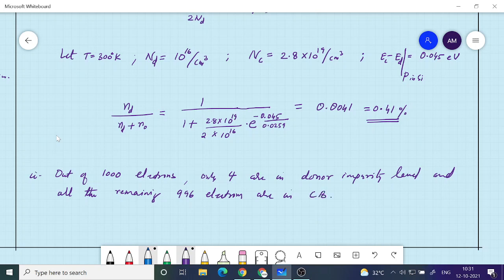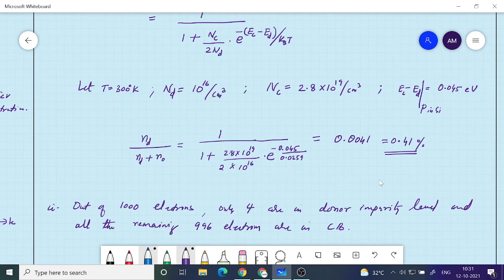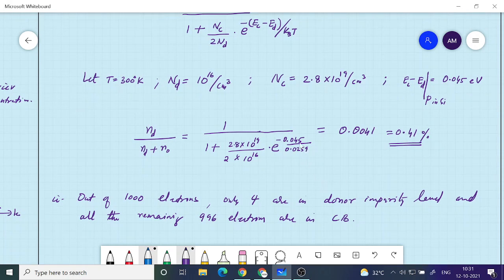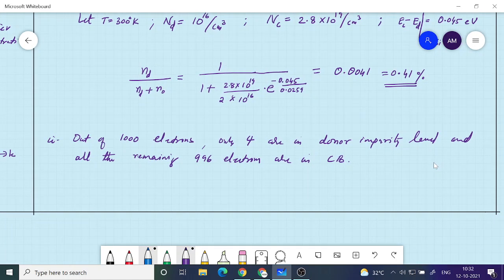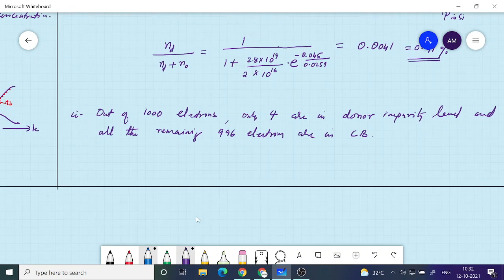So that is a very important insight one should have at room temperature. This calculation is for room temperature, but if you assume a much lower temperature, then this exponential can be very, very small, and that can challenge the 1000 here. When you multiply that exponential with 1000, it can become very, very small, and then this percentage can be increased. But even at a very cold winter temperature, this factor is still going to be very, very small. So we can safely assume that all the electrons are going into the conduction band,